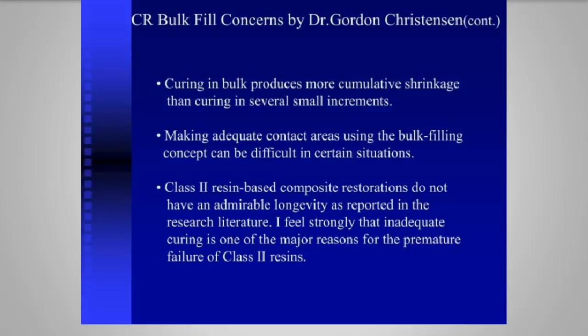Now, if you look at Dr. Christensen on the follow-up on the backside of this, he says that bulk filling can be difficult in different situations. And his summation is he strongly feels that inadequate curing is the major reason for premature failure of class 2 resins. And this could be bulk filling as well.